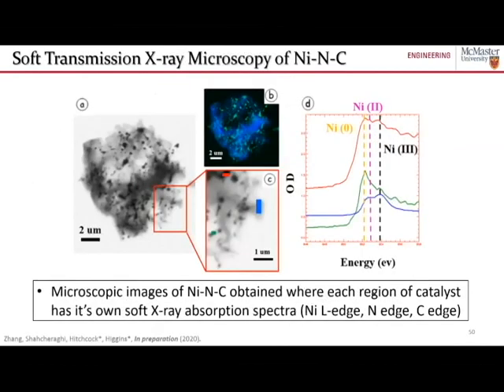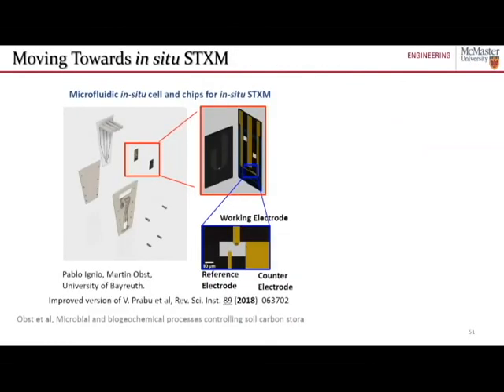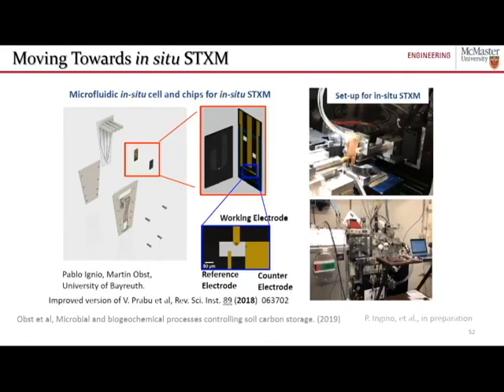So we've taken some of these nickel catalysts. You can see it here. I'm not going to dive into it too much, but ultimately we get a microscopic image of this catalyst material with every region in this material being correlated with an X-ray absorption spectroscopy spectra that can give us understanding of what species exist in this catalyst and where. We're also taking it one step further using some electrochemical cells developed at the University of Bayreuth by Martin Obst, Pablo Ignio and his team. And so it's taking these materials, depositing them onto working electrodes, flowing electrolytes and our reactants in, and doing STXM of these materials under reaction conditions.